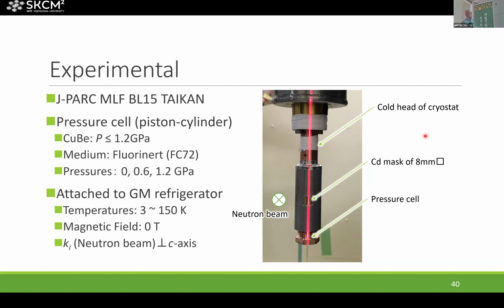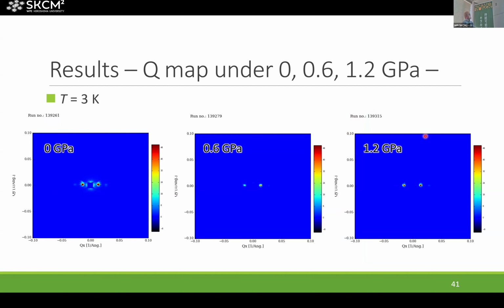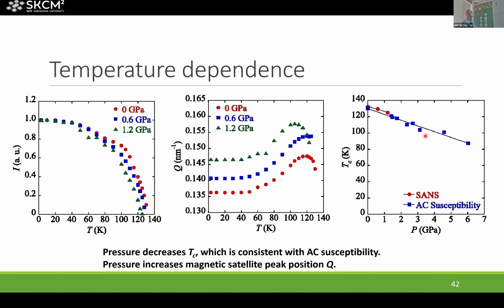Then we measured the pressure effect at temperatures between 3 and 150 K, and we applied pressures of 0.6 and 1.2 gigapascal. Here are the results. We successfully observed the two peaks from the conical phase at each pressure. From these results, we can extract the temperature dependence of intensity and propagation vectors. We found that the transition temperature decreases with increasing pressure, consistent with the other sample measurements, and also that the propagation vector increases with increasing applied pressure.